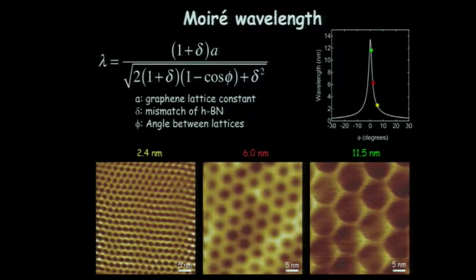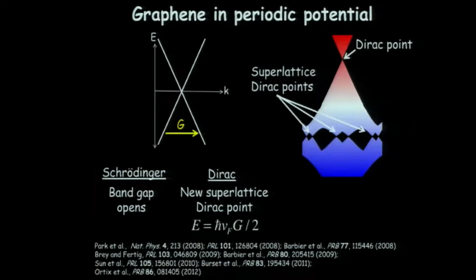And so we go from 2 nanometers to 6 to 11.5. And you can see already here that the Moiré pattern, sort of what it looks like, is changing as we change the wavelength. It's becoming a little bit sharper here on these boundaries, which I'll come back to in a few slides, on what's happening in these very long wavelength Moiré patterns. But I just wanted to spend an interlude for just a minute on this superlattice potential that's arising here. And so because we have this Moiré pattern, right, that does mean that there is some interaction between the graphene and the boron nitride. It's not actually acting as sort of an inert substrate.